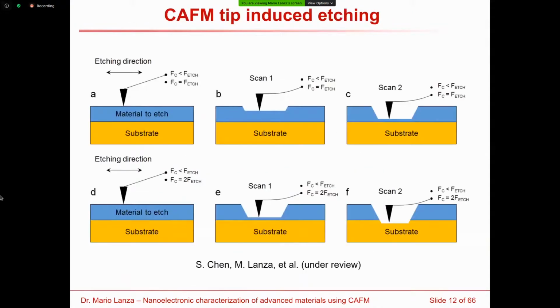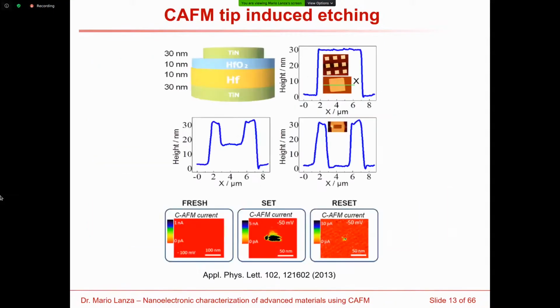So one method that can be employed is the use of the tip of the AFM to etch this electrode. And then if you do that, you can etch all the volume of the top electrode, and after that you can see the size of the conductive filaments across the dielectric in both states, for example, in high resistive state and in low resistive state, and you successfully can see what is below this electrode. The tip can be used to etch the top electrode of the device.